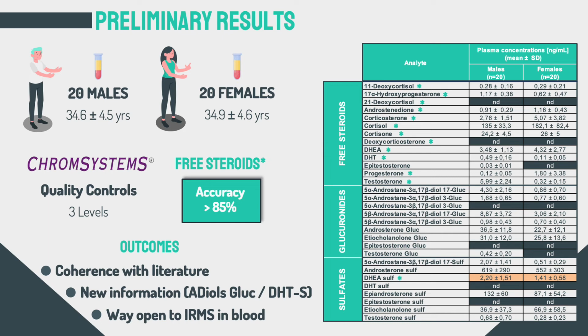and highlighted novel information regarding both the circulation of 5α-androstanediol glucuronides, with the 17 glucuroconjugated forms being the most concentrated, and the impossibility to detect some androgenous metabolites, such as DHT sulfate. Finally, the high concentrations measured for some doping markers, such as epiandrosterone sulfate, confirmed the possibility of developing IRMS analysis in blood, as recently proposed at the Manfred Donike workshop.